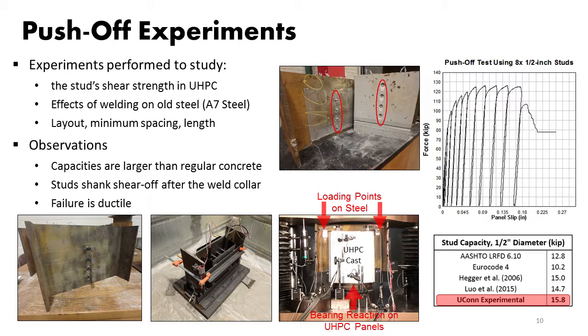And you can see in here the sample force displacement curve. Our capacity is comparable with the equations proposed by a group of researchers in Japan and some researchers in the US. And they are definitely larger than what AASHTO predicts for reinforced concrete, even if you use a very large f'c. And Eurocode also underpredicts the capacity.